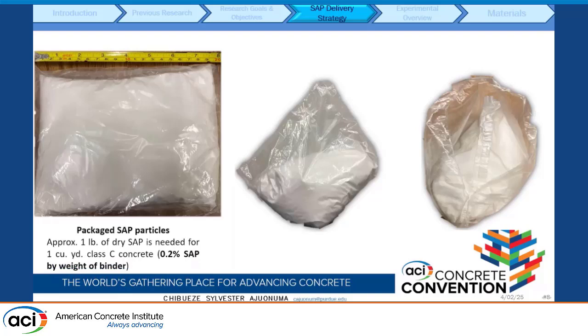For the second objective, how do we deliver SAP in the field? We prepackaged SAP in dissolvable bags. These are water-soluble bags, which we just store into the mixer. It automatically dissolves. So we're able to prepackage 1 pound of SAP in this bag, and this 1 pound of SAP is equivalent for 1 cubic yard of concrete, and we dosed at 0.2% by the cementitious weight.